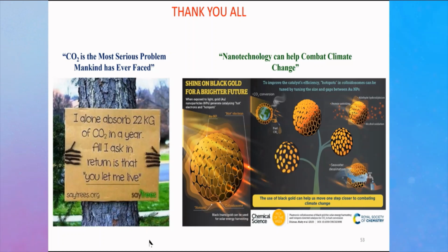Anis Rao: I might have missed this. Using Raman spectroscopy, the surface temperature was estimated to be around 150, but you were able to reduce the CO2, which is at 400. I guess I am missing something. Yes, you're missing something. The 400 degrees Celsius was done using the defected silica, whereas the 150 degrees was done using the gold nanoparticle. It's our goal to combine these two, to do the defected silica catalysis at 150 degrees Celsius, and that is very much possible.